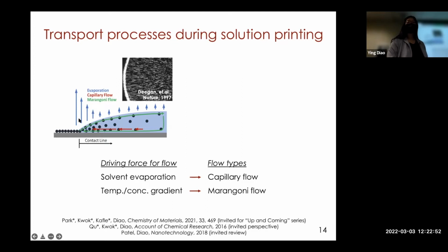The evaporation rate radically increases when you get to the triple phase contact line. Because of this evaporation profile, it pulls the ink from the center to the edge through a flow called capillary flow, and that drives the particles to deposit on the edge. During inkjet printing, the physics is essentially the same.